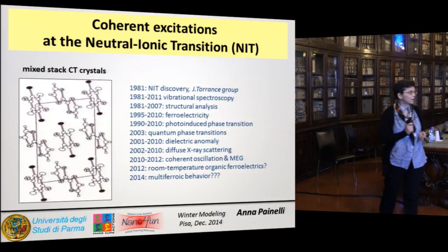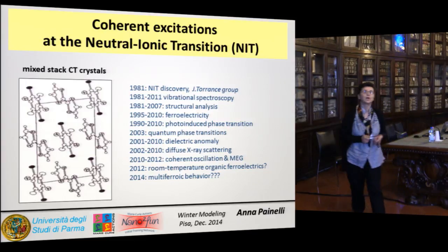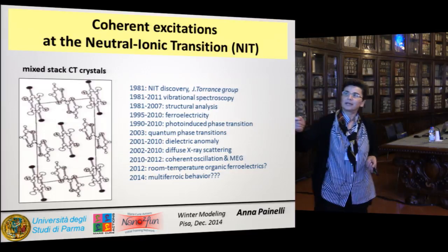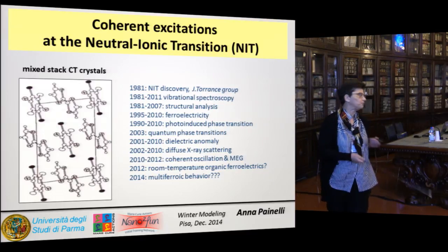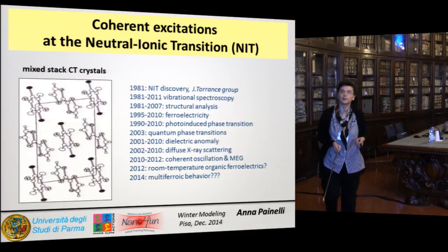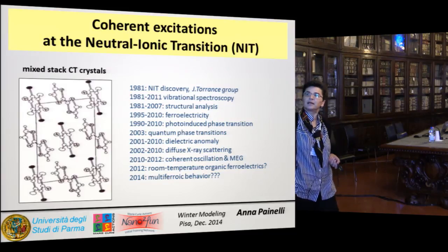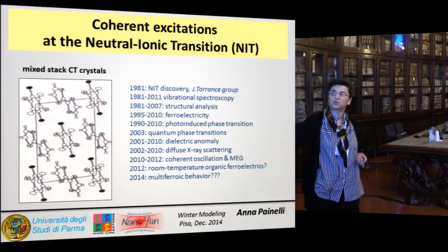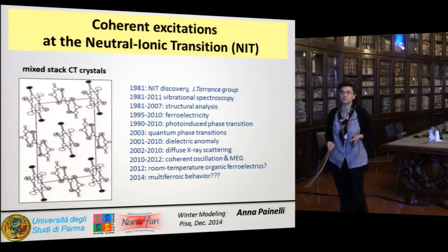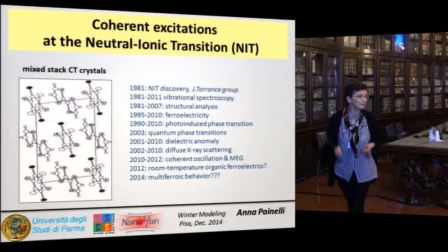In these systems, which are organic molecular crystals, so like anthracene in a sense, there are no heavy atoms, nothing, you can reach a dielectric constant of the order of 600 or 800 or so, which is really unusual. And then very recently there are hints of room temperature organic ferroelectrics, but I must say I don't believe too much this result, even if it is a Nature paper, or possibly because it is a Nature paper.